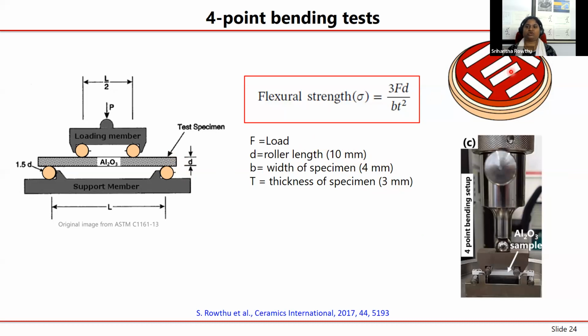So again, we will use the slip casting method, because these specimen dimensions are different as compared to the samples that we need for tribology. Once we get these long specimens, we can put the specimen here and we can apply a load here. And then you see that this is 1, this is 2, 3, and 4. There are 4 points. That's why it's 4-point bending. So we can simply break it and find out what is the flexure strength for this particular sample.